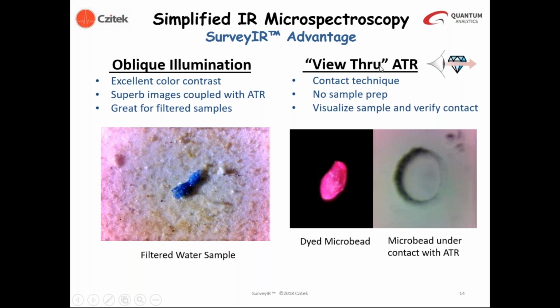We can couple this illumination method with a diamond ATR, which we can observe samples through. Diamond is transparent to visible wavelengths as well as infrared wavelengths. So we can actually view specimens through the diamond and then also observe contact with the diamond crystal like we see on the right-hand side. This allows us the confidence that we're making contact with the sample and we're analyzing the area in which we intend to analyze.